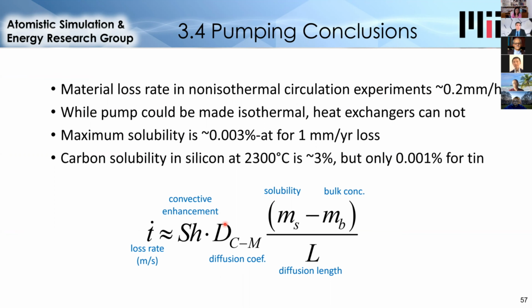And so I tried to estimate what is the maximum solubility we could tolerate in a system like this to try to see if there's other materials we could consider. So if the loss rate is in meters per second, or time, distance per time, I set a maximum of 1 millimeter per year of material loss. And this results in a solubility, which is here, of 0.003%. This is 1,000 times lower than silicon, which shows why we saw such fast degradation.